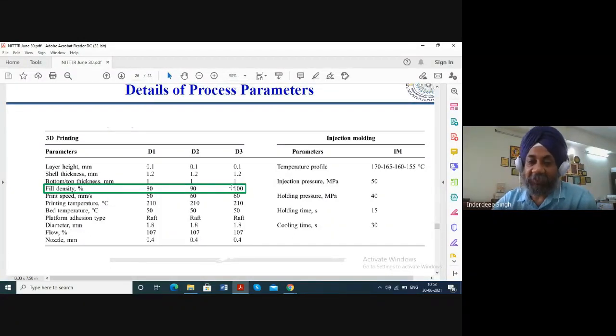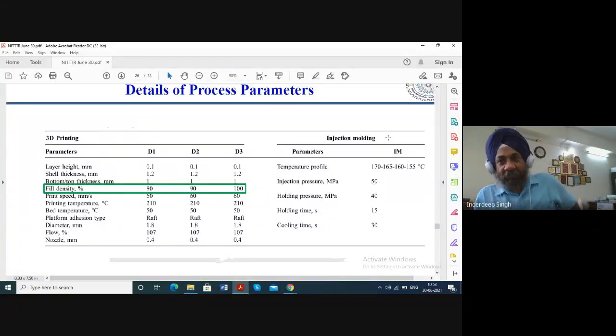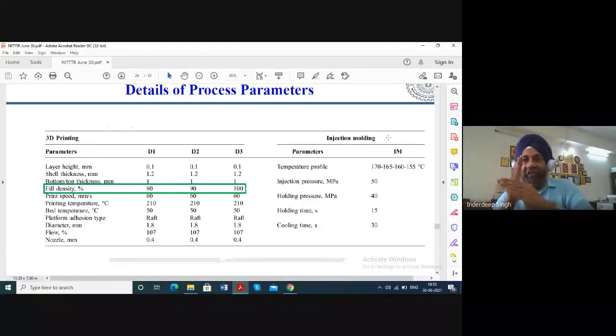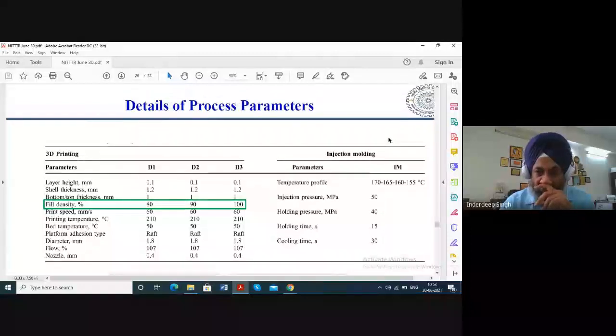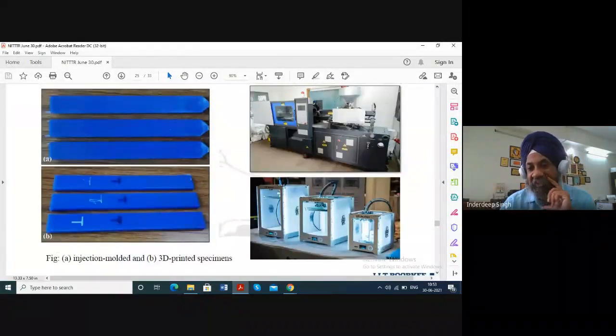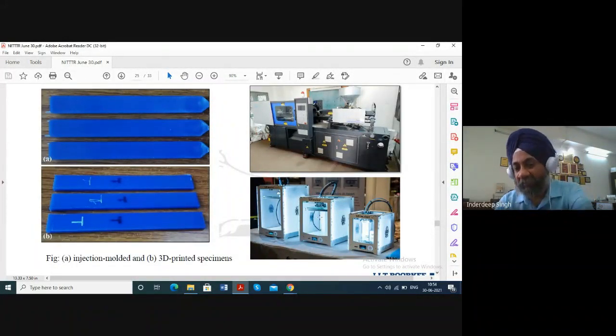Although it is a well established fact that if you have a fill density of 100, it is expected to perform better. And then these were the optimized parameters which we used for our injection molding setup for the same PLA material. As I have shown you, we can pelletize the strand, extrudate, or the filament into smaller pellets. So the same setup we used to pelletize the PLA filament, because here, if I go back, in this case, we will be using a filament. A blue color filament is used, that is a PLA filament or a wire, which is used as the raw material.